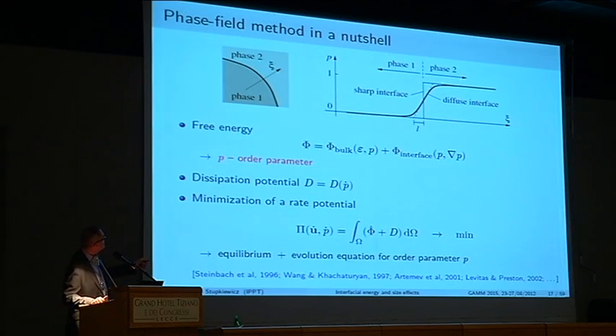So how do we use this smooth representation? We introduce the free energy, which is composed of the bulk contribution, which depends, for instance, on the strain and on this order parameter P, and the other contribution, which is defined in the volume but which describes the interface, and it depends on this order parameter and its gradient. And doing that, combining it with some dissipation potential and formulating a kind of minimization for a rate potential, by minimizing this we can get equilibrium equations by minimizing it with respect to the displacement velocities, and also evolution equations of Ginzburg-Landau type for the order parameter.